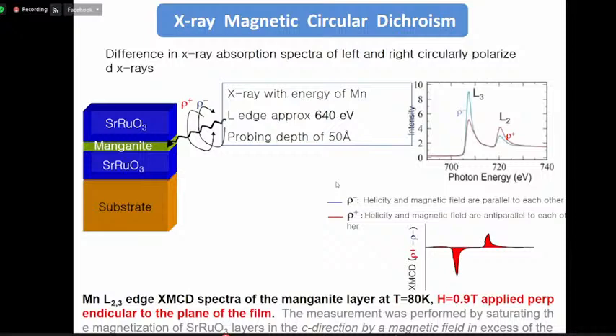Then I used X-ray magnetic circular dichroism. This is a tool to see magnetic properties in buried layers like this. The manganite is below the strontium ruthenate. If you use SQUID, we just see the total magnetization. But if we tune the energy of the X-ray, then we can see only the manganite layer. In this case we tune the energy around 640, the absorption edge of manganese. So we see only the profile of manganite.